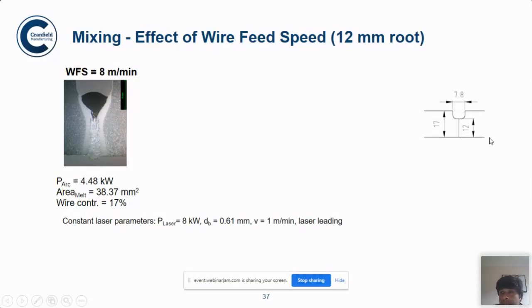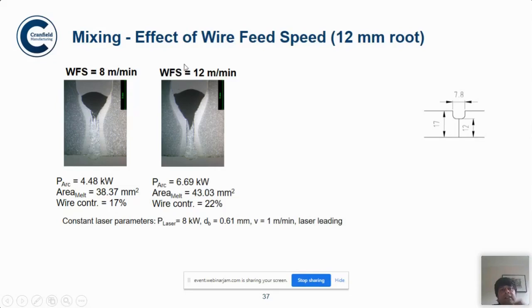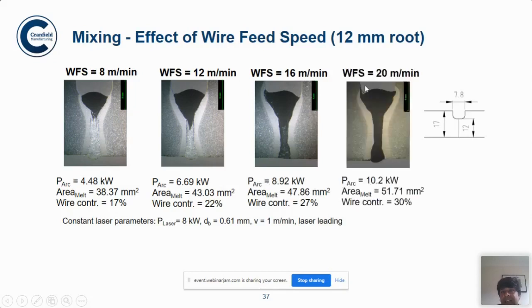On the right hand side, I'm showing you the bevel configuration. The 12 millimeter is the depth of the bevel. And now you can see here there is huge segregation of metal. So basically arc and laser power don't couple with each other at all. So now we increase the wire feed speed, which means we increase the arc energy. Arc energy is shown here, as you can see, from 4.48, now it is 6.69. And slowly as we increase, you can clearly see how the mixing is accomplished. So now, as you can see, using laser plus arc, you create a completely homogenized structure, a completely homogeneous weld metal, which will be as good as it can be if you use a normal arc process.